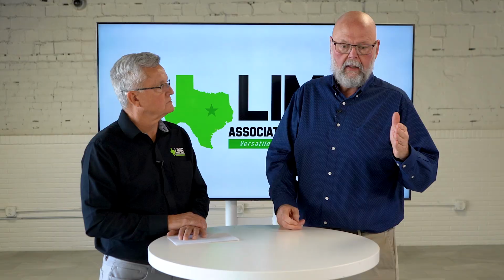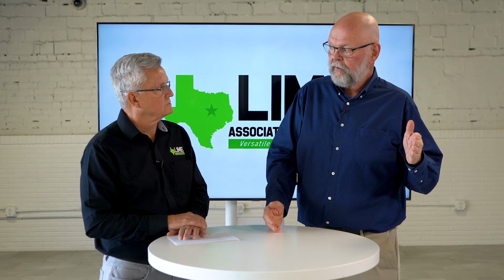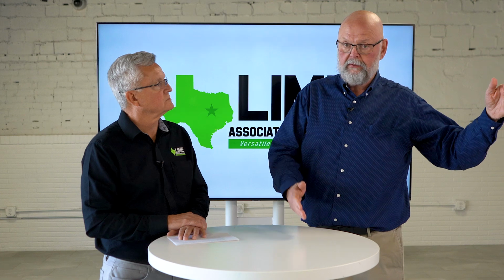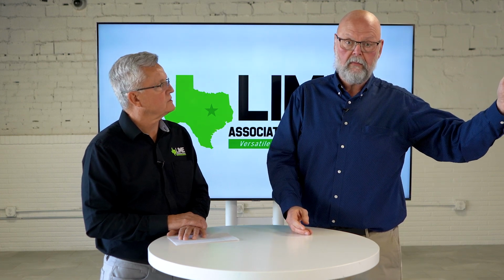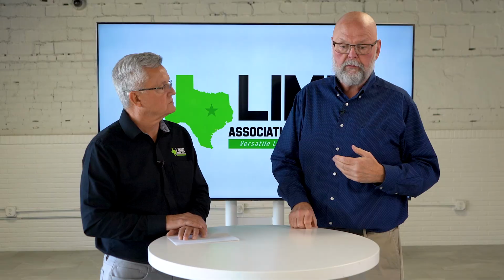So I add calcium, I change my orientation, I start to dissolve it, and I cement it together in the new orientation. The good thing about it, it's slow. Great, I want it really fast. Well, what that means though is it's going to be stronger in a month than it is on day one. It's going to be stronger in a year than it is in a month. It's going to be stronger in 40 years. It slowly gains strength. But also if you get cracking in there, because those tendrils keep dissolving or forming, as long as you have calcium, alkalinity, and the clays there in water, you can heal.